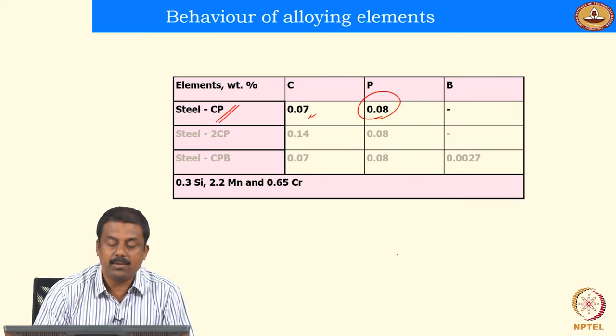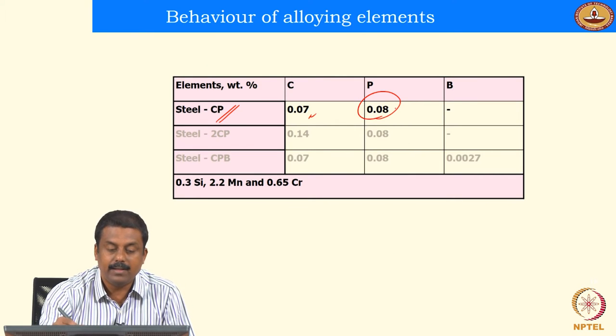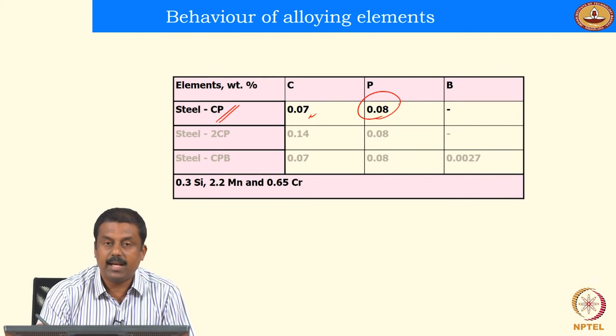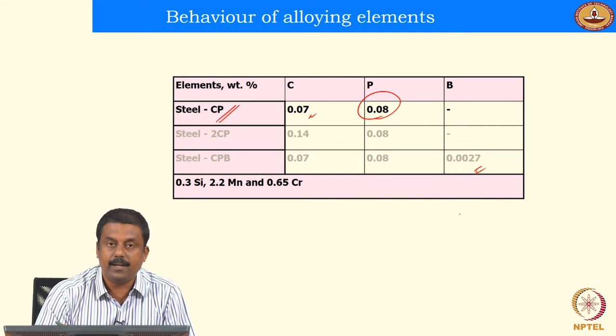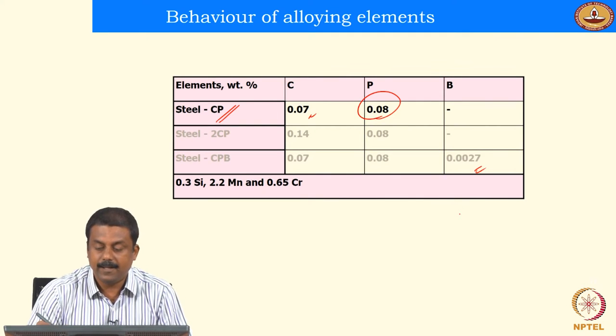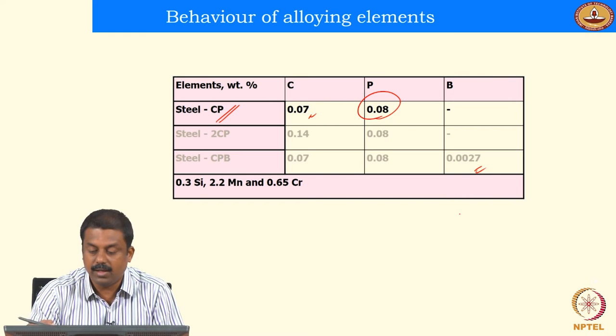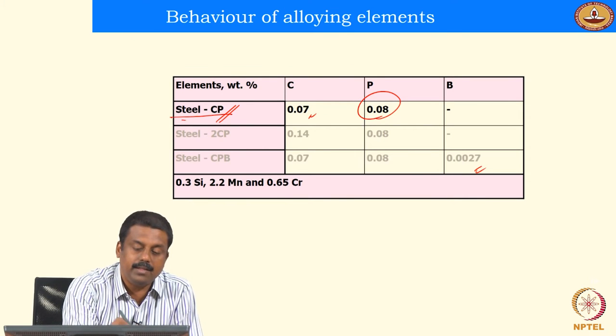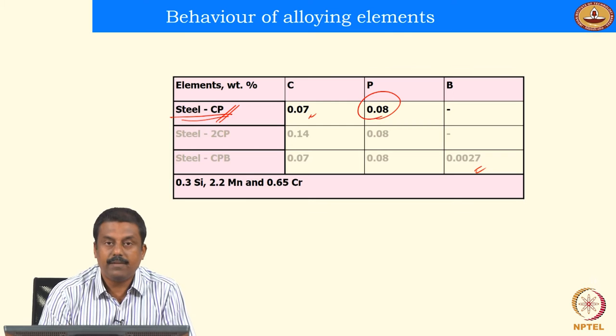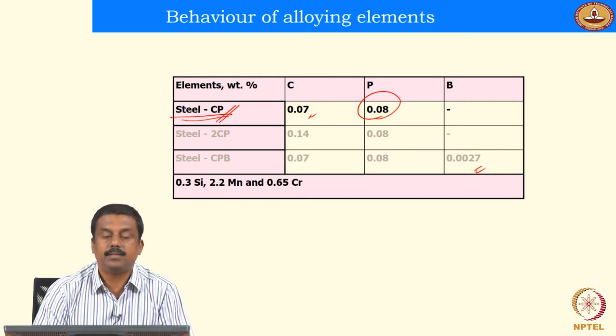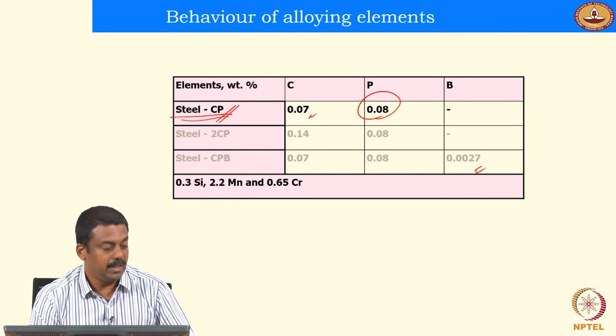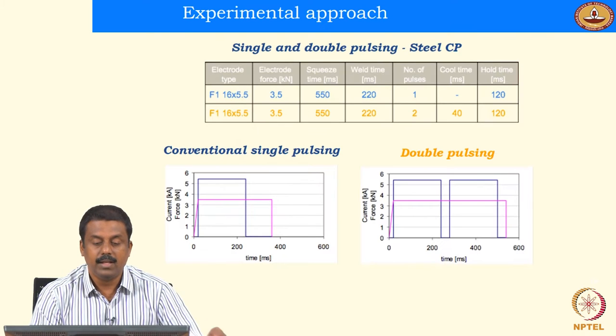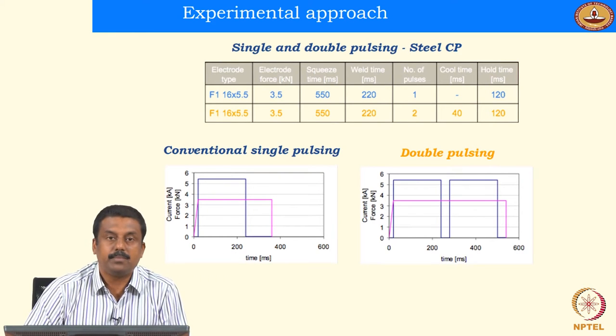So now we need to make sure that the weld of the steel CP doesn't fail in the weld zone. We can add phosphorus and boron to avoid the failure of the weldments at the interface, in order to achieve the full plug failure. But now the steel chemistry is fixed. Say, for example, we have only steel CP, we cannot add boron. Can we modify the weld thermal cycle in such a way that we can improve the mechanical properties of steel CP? Okay, it is possible. We look at one modification in the weld thermal cycle. Before that, I will explain how this modification can be carried out.